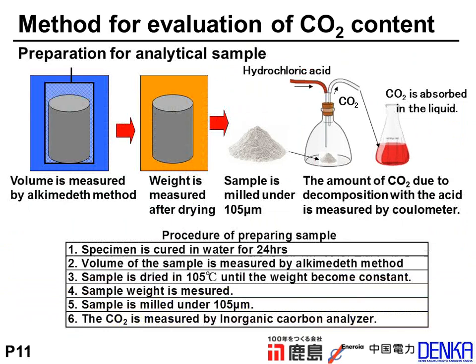The preparation of the analytical sample from the concrete specimen is below. The specimen is cured in water for 24 hours, and the volume of the sample is measured by the Archimedes method. After that, the sample is dried at 105 degrees Celsius until the weight becomes constant, and the sample weight is measured. And the sample is milled to under 105 micron. The content of carbon dioxide is measured by the inorganic carbon analyzer.